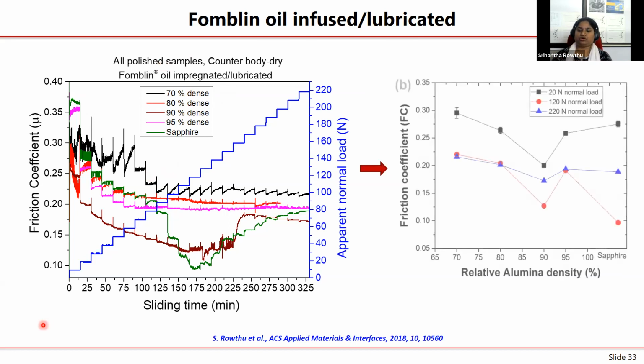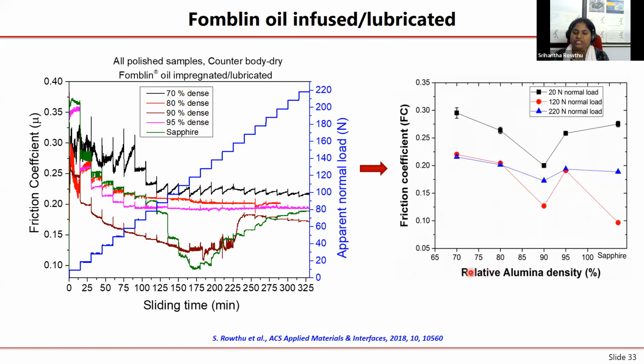Now to make it easier for you, we can plot it in this manner. Right now it is as a function of the sliding time, but I wanted to understand which is a better density for the substrate. So therefore, I'm going to plot my friction coefficient as a function of density of alumina, that is 70, 80, 90, etc., and for different loads. Whatever three loads we have plotted, you can nicely see that there is a dip at 90%. That means my 90% alumina density seems to be an optimal density to yield the lowest friction coefficient.